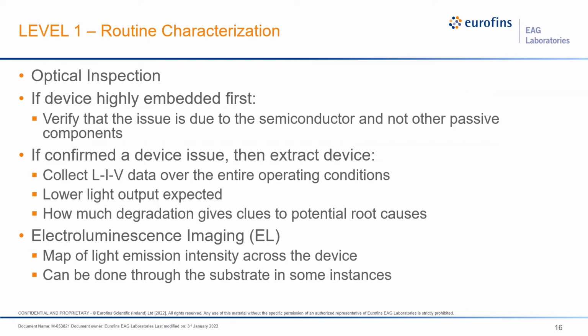And so this takes us to level 1 routine characterization on the sample. So we'll do some optical inspection first. And then if it's highly embedded like it was, we need to verify the issue is due to the semiconductor and not the other passive components. So we've done that, and to confirm it's a device issue, we extract the device. So over here is a picture of the de-encapsulated die, still with the bond wires intact, if possible. And so then we're going to collect IV data over the entire operating conditions for the device.